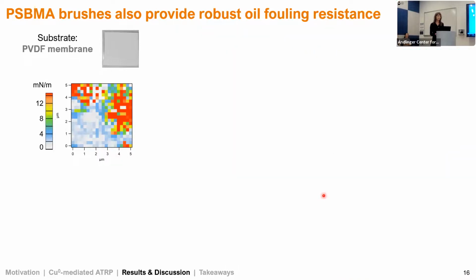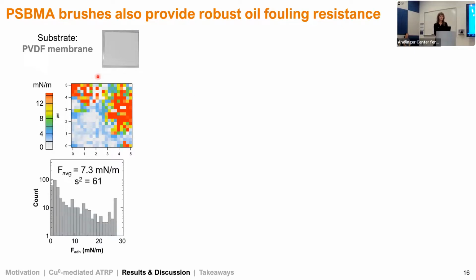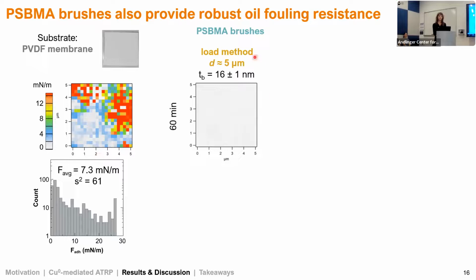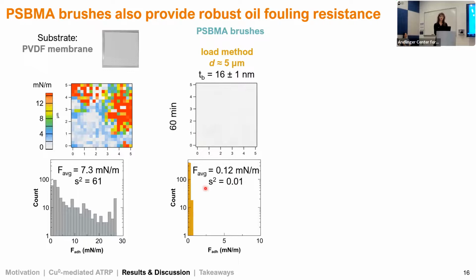So that's organics. We also looked at, as I mentioned, a model oil foulant. Here we have the adhesion force map for our model oil foulant on the unmodified membrane. We can see that this membrane has very low fouling resistance to oil, which we expect because it's a hydrophobic membrane. Looking at the histogram, the average adhesion force and variance are very high for this membrane. For our brush modified membranes, starting again with the load method, we've improved fouling resistance dramatically. At this scale, we don't see any colored pixels. Looking at the histogram, the average adhesion force is decreased by an order of magnitude, and variance is again close to 0.